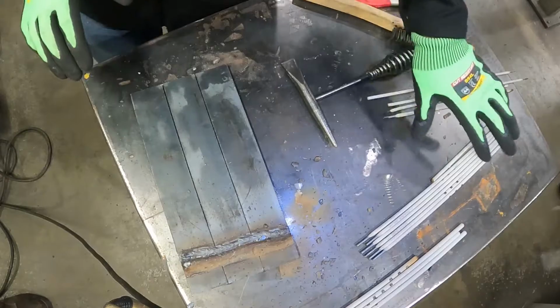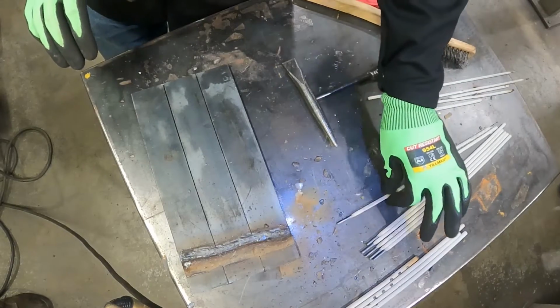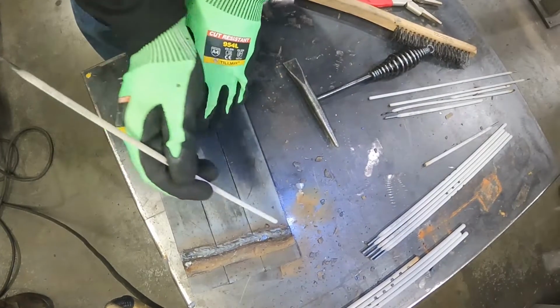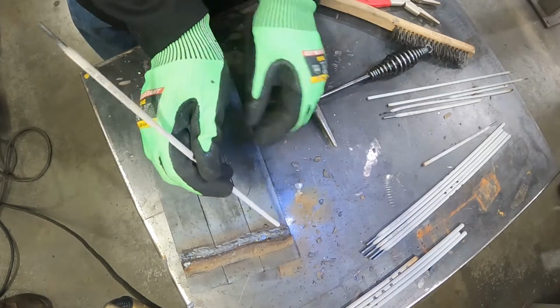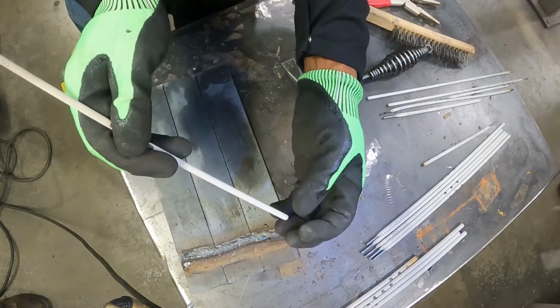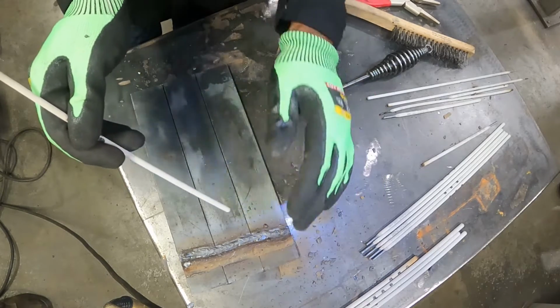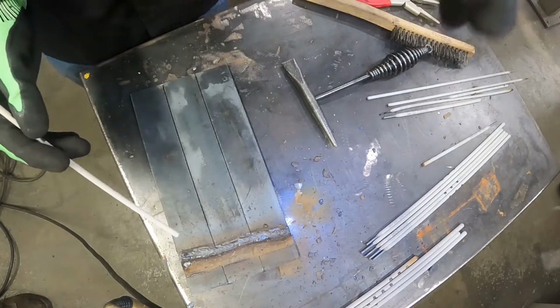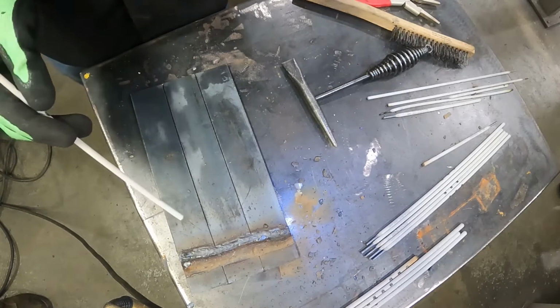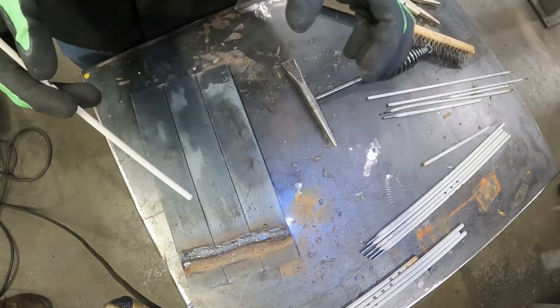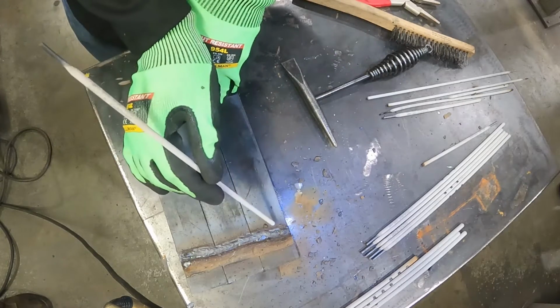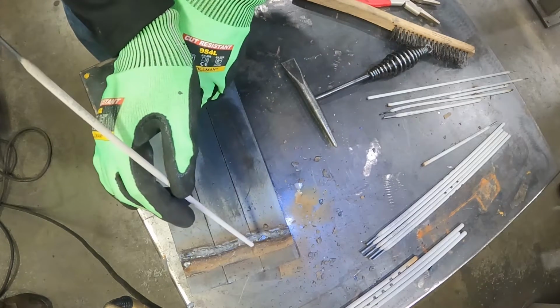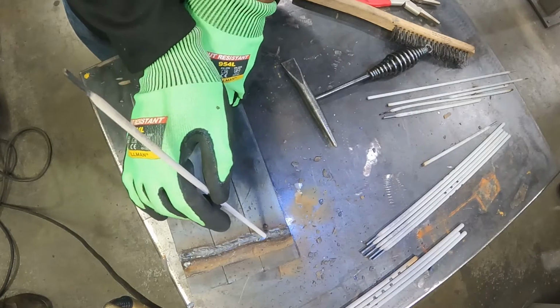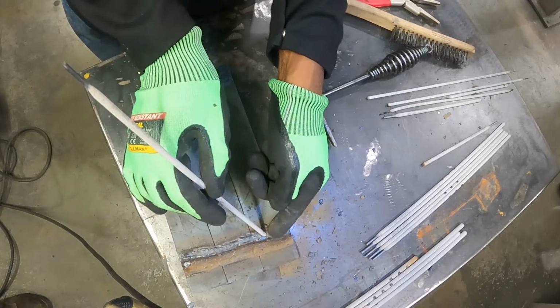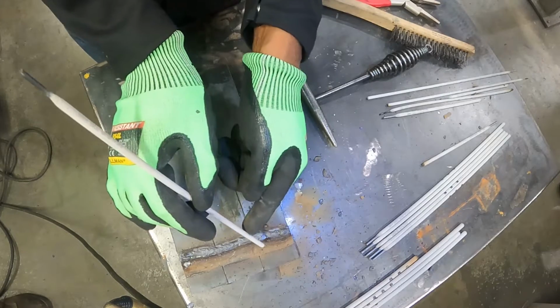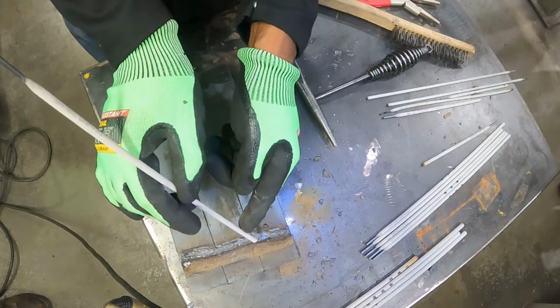Very good. So what we observed was that when he first struck the arc, right, he was a little bit long. So it looked like the metal was balling up on the end and then dropping down to the surface. So that's an indication that you're too far away. Okay, that means your arc length is too long. Okay, and then as he progressed through, we noticed that he would get close, but then he would wait a second and it would burn up. Then he'd get close again, and it would burn up, right?